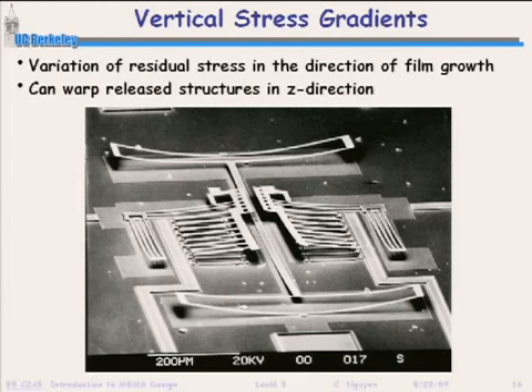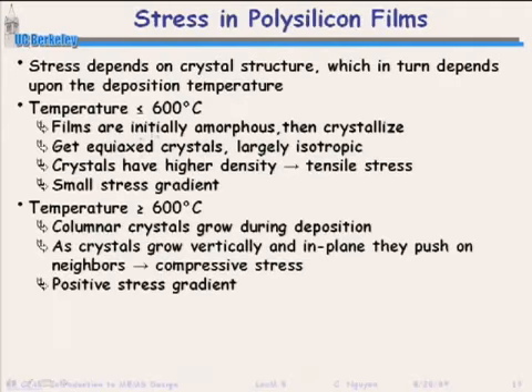So let's talk about stress a little bit. Stress in polysilicon films. Why do we have vertical stress gradients? A lot of it has to do with how the film is grown. Films are initially amorphous. It depends on temperature in this case. If you're depositing at less than 600 degrees C, which is what a lot of MEMS people do, and my group does this now, the films are initially amorphous and then they crystallize. You get equiaxed crystals, which means it's largely isotropic. You don't have one direction dominating. You get crystals that are sort of random all over the place. The crystals have a higher density, which means they're packed a lot more, and so you get tensile stress.